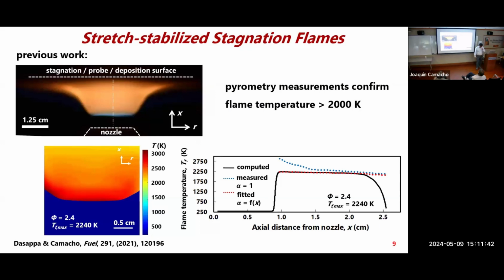Previously, we have showed that this flame stabilization mechanism does not depend on heat loss flame anchoring. Because of that, it burns hotter than other laboratory flames, like a Bunsen flame or burner stabilized flame. This one is stabilized at this steady position due to aerodynamic kinematic balance. Because of that, there's much less heat loss, and we can burn hotter.